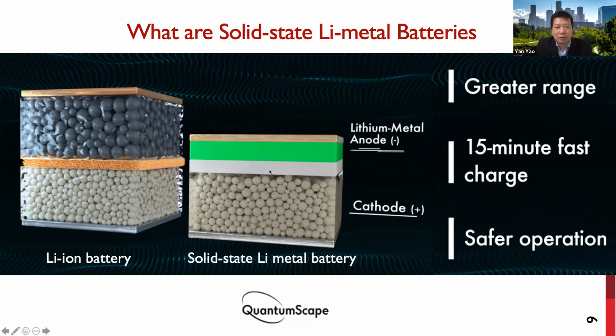ceramic separator. You could use lithium metal as the anode, or in the anode-free design, lithium metal could be plated during the initial charge process. Due to the reduced volume and mass compared to lithium-ion batteries, a lithium metal battery can potentially double the energy density from 250 to 500 watt-hour per kilogram. So this could enable a greater driving range, 15-minute fast charge, and safer operation due to the non-flammable electrolytes involved. However, it has been extremely difficult to do so, particularly plating and stripping lithium metal at such a high rate without any side reaction has been extremely challenging.